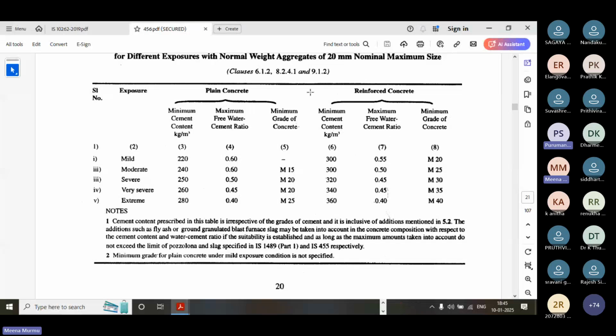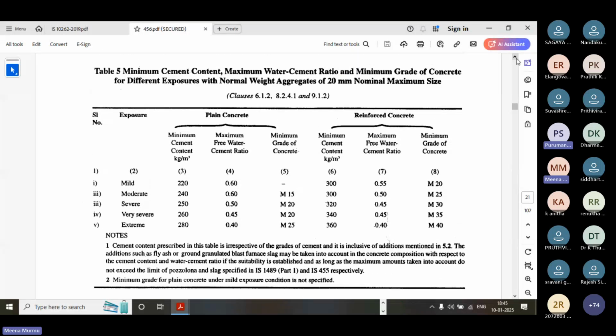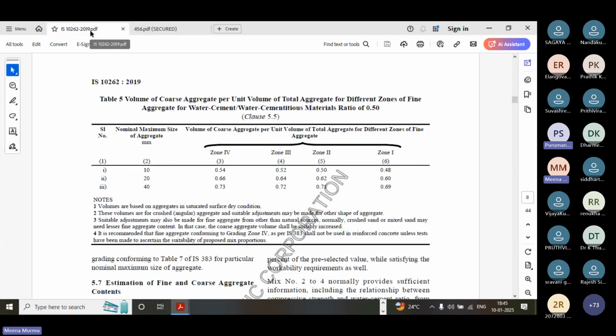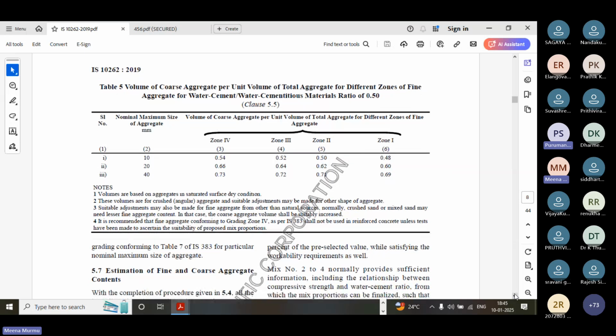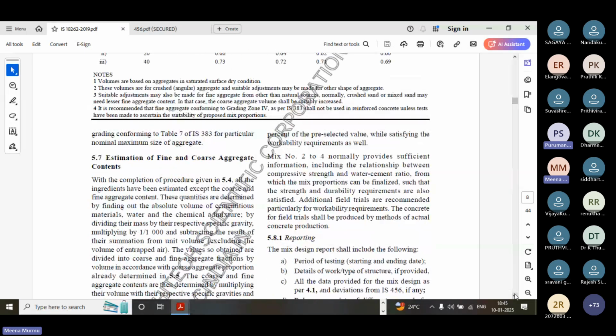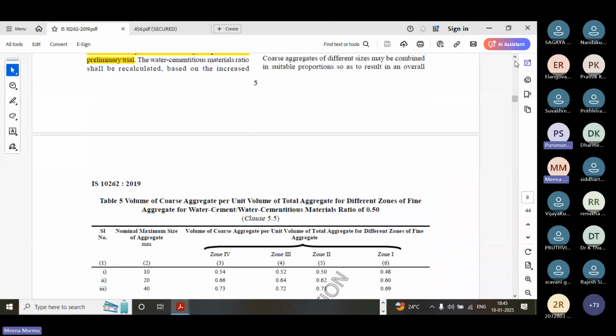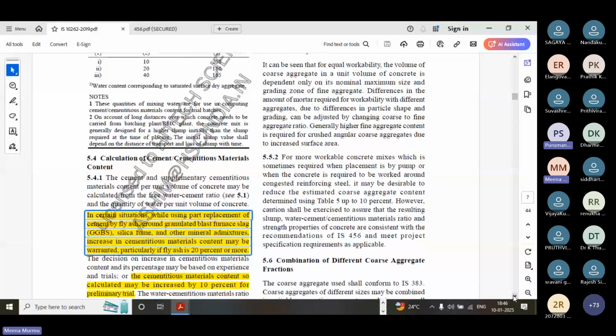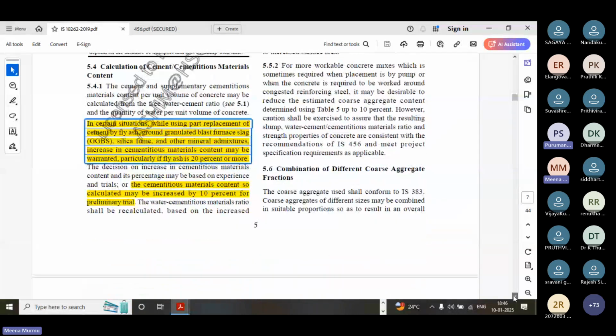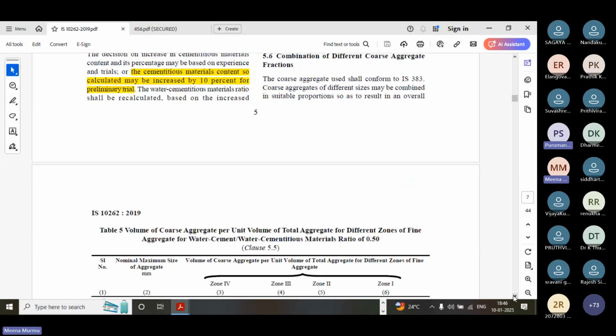So here this is the table, we have to cross verify with Table 5 also. This side is given reinforced concrete, this side is given plain concrete, and we design for reinforced concrete. So here for M30 we are talking, the maximum water cement ratio is 0.45. So as per the curve we have taken between 0.4 to 0.45. So whatever water cement ratio we have adopted, it is less than 0.45. And that's why according to 0.42, the volume of coarse aggregate we have to take, that one we can choose from Table 5, and we have to recalculate also. So this is given in the code itself.